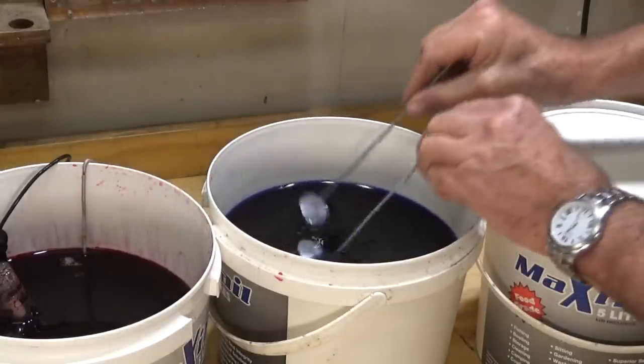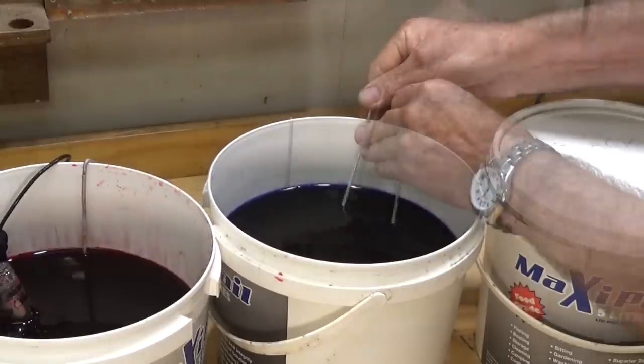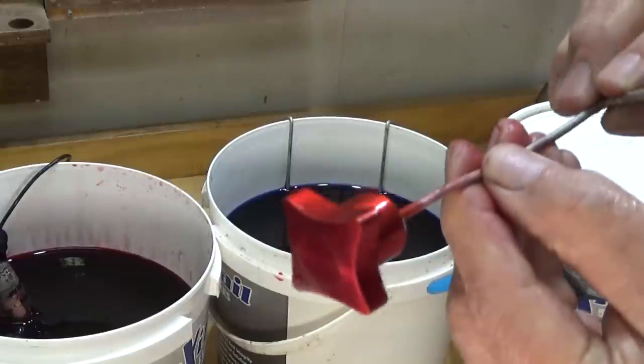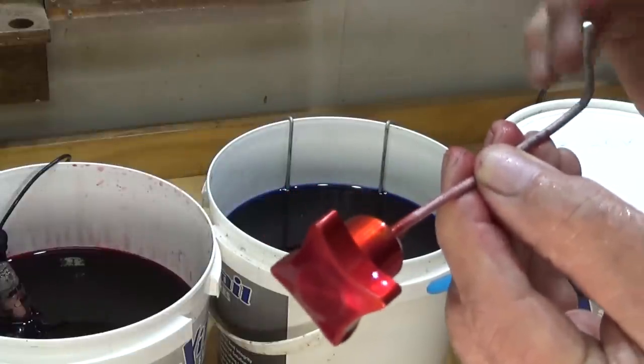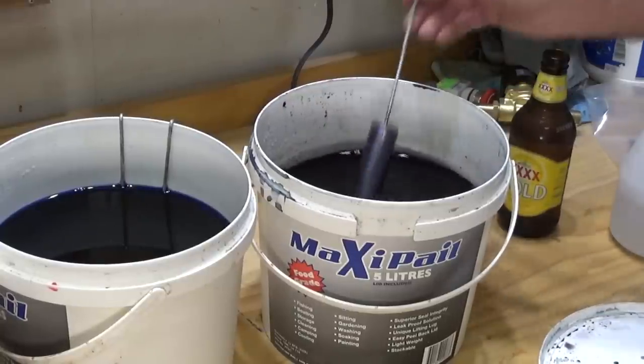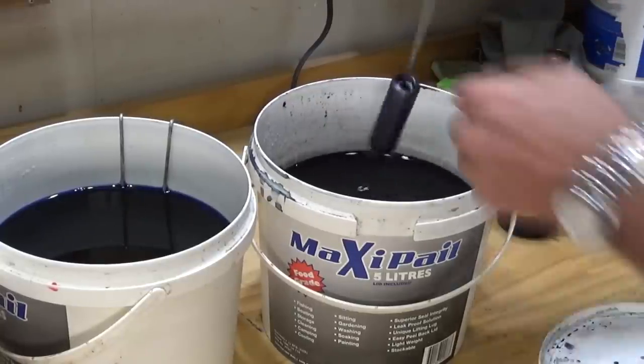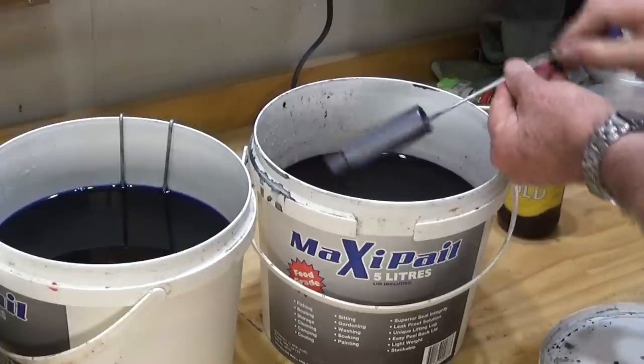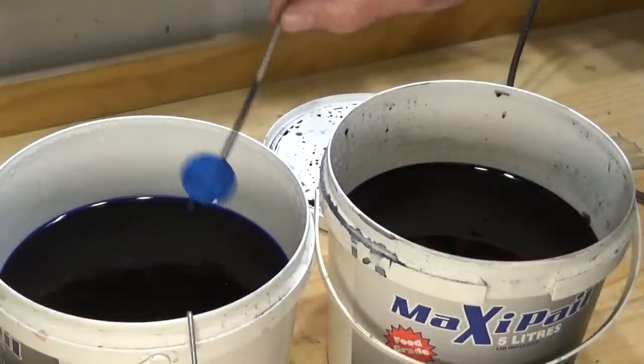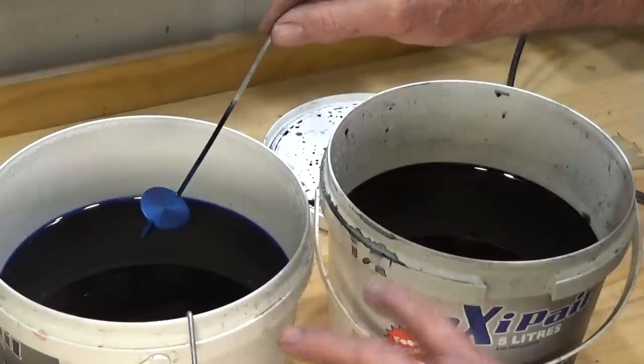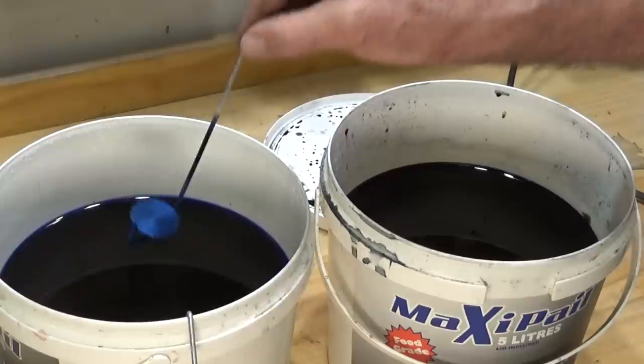These parts going in the blue dye will take a bit longer because this is room temperature. You'll see that there isn't that immediate change. So I'm just going to let them sit there and we'll just check them periodically. But that will take a lot longer. I think our red part's done. I'll just rinse that off again. The colour is a little bit darker than the other parts that I've done. But some of the colour will leach out when we do the last step which is the sealing. There's the handle in the black. Once again this is room temperature dye. So it's going to take a while. Well there's the blue parts that I've done. That's taken a lot longer, like an hour. That's the difference between heating the dye or leaving it room temperature. But they're pretty much the colour I want. What we need to do now is rinse these and get them into a container of boiling water.